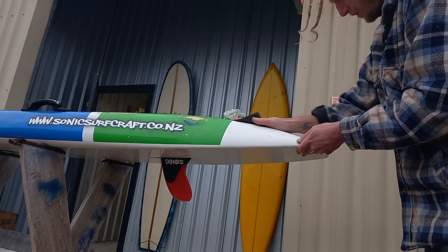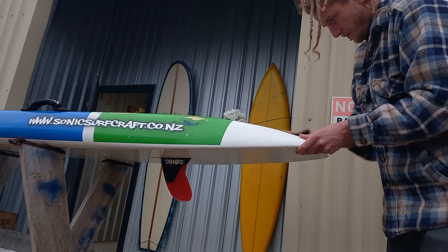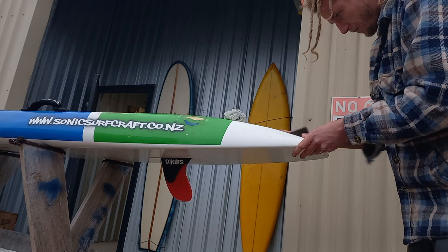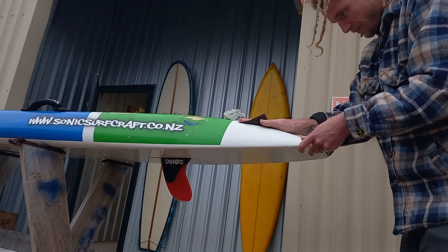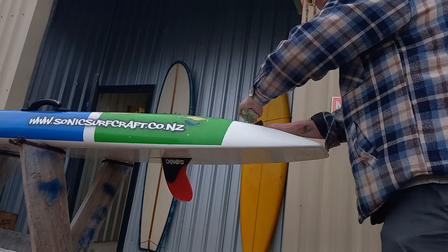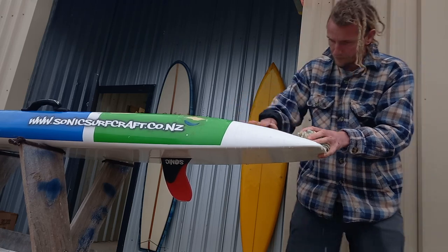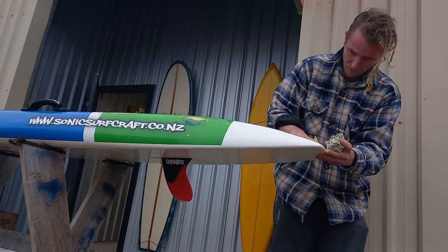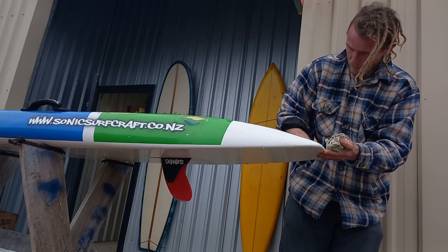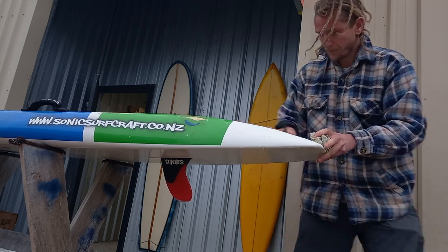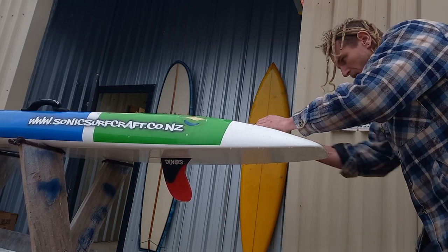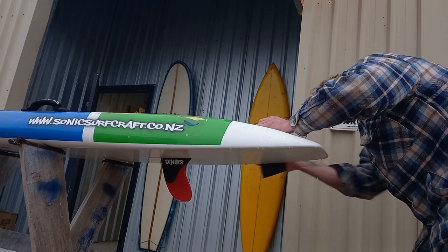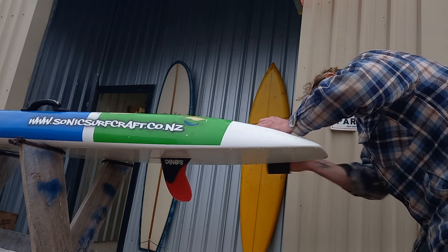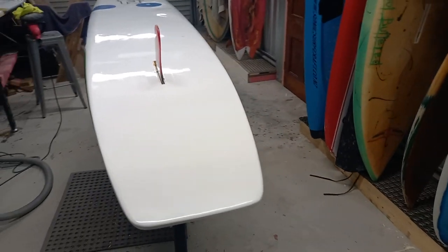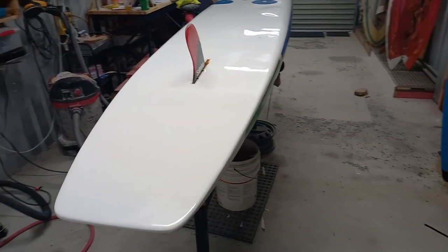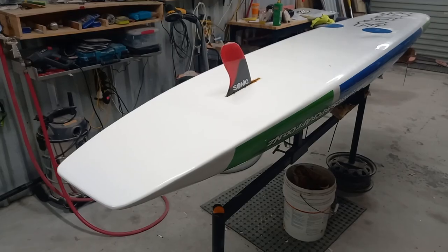So now we're wet sanding with 800, and the only thing we have to contend with is sanding our paint job smooth, getting rid of any orange peel, making it nice and flat, and the only scratches left on the board should be from our 600 wet sanding that we did before painting. So we can get rid of those 600 scratches with our 800, flatten out our paint with our 800, and then go on to polishing. With only 800 scratches left, we can polish them out, and this is our final result.